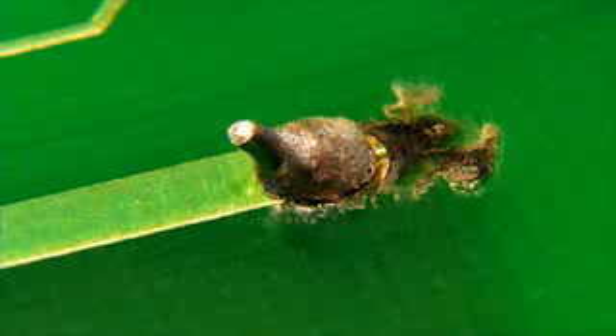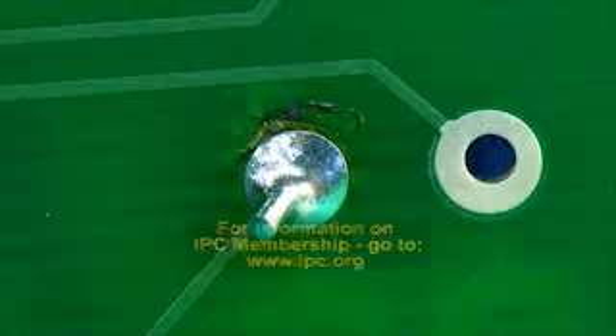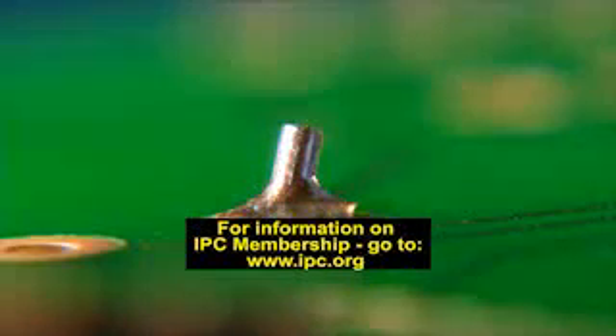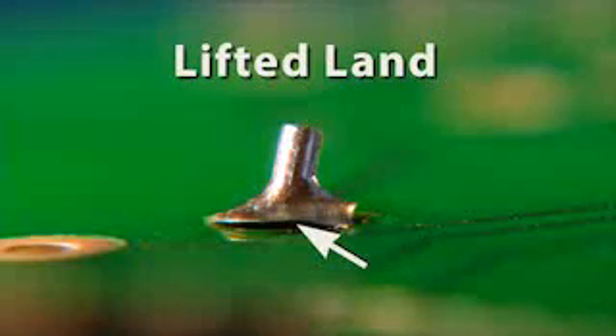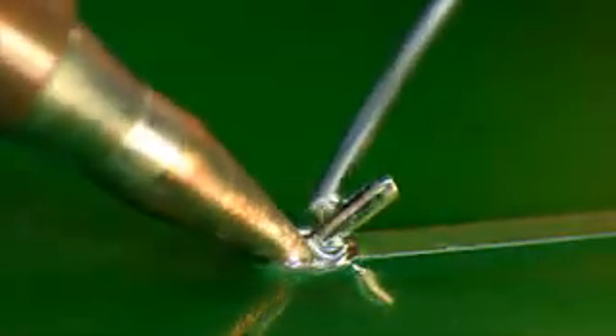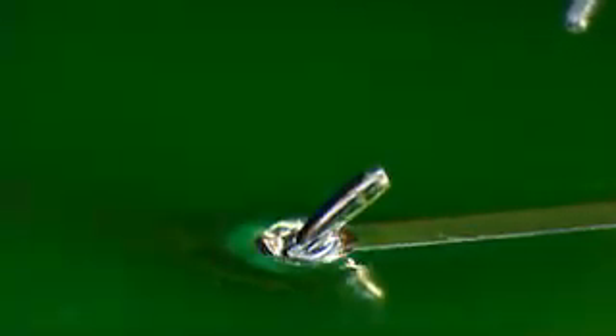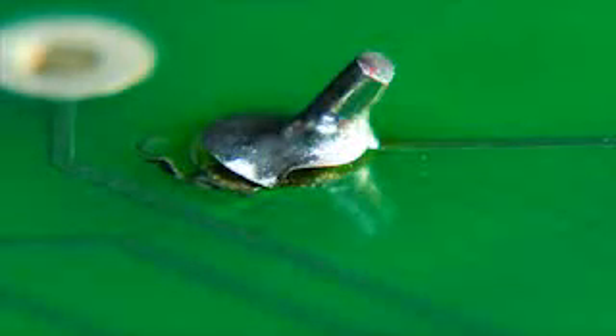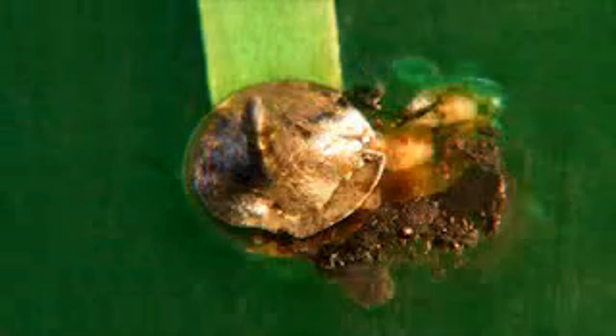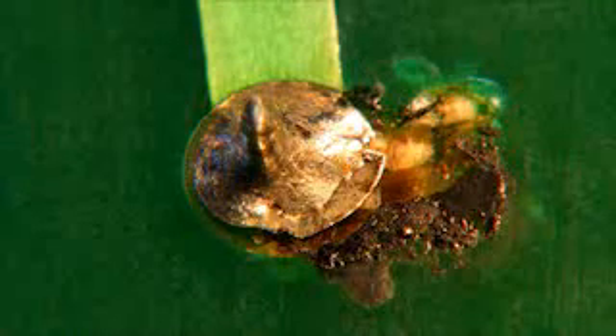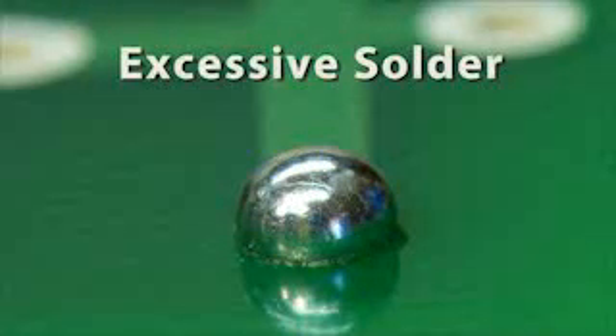Here we have a burned board. This was caused by contact with a hot soldering iron or too long a dwell time at the proper temperature. These are some additional examples of thermal damage. And this is a lifted land. Lifting can be caused by pushing or pressing down with a hot iron. Failure to allow cooling between heat applications can also result in a lifted land. Lifting can also indicate that the iron was left on the board for too long or that too high of a temperature was used. This joint has excessive solder.